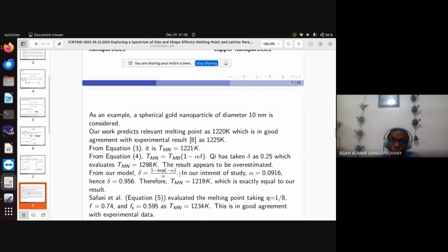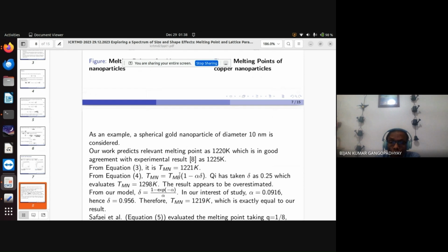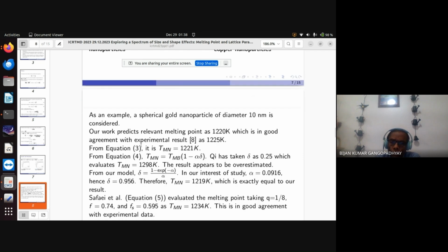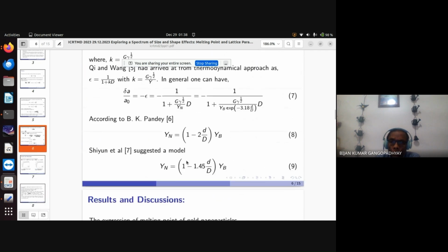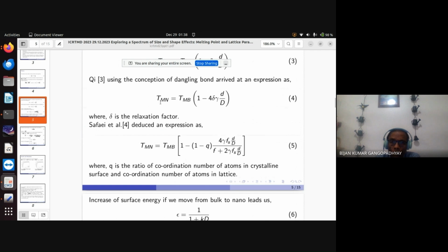And so, to justify, we have chosen an example of gold nanoparticles of 10 nanometer. In that case, our plot for this relevant melting point at 1220K is identical with the reported value 1225K. And from equation 3, it is 1221K. And this is very important. This equation, I just want to slide back to the previous slide. This one. So this delta is a very important factor.